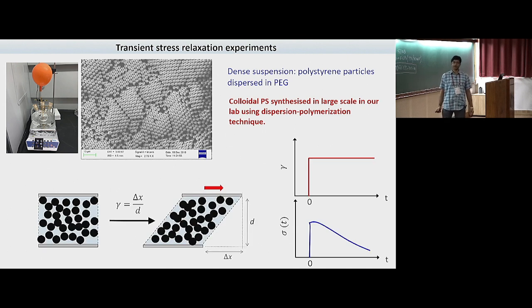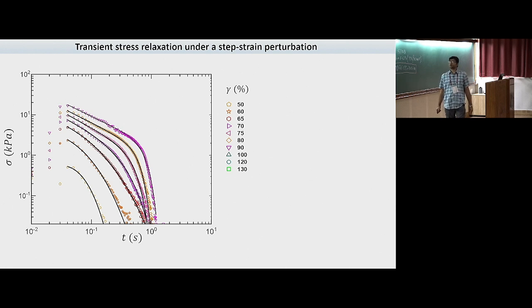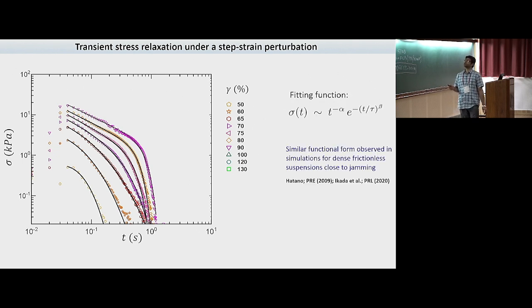We take this suspension and apply a step strain deformation, and we study the stress relaxation in this system. These are the results for different step strain magnitudes. As we increase the step strain magnitude, the peak stress increases and the relaxation times also become slower. But you notice that this is pretty fast relaxation; the entire process completes within a second or a few seconds. The solid lines are fits to a power law cut off by a stretched or compressed exponential, because this beta value is greater than 1.